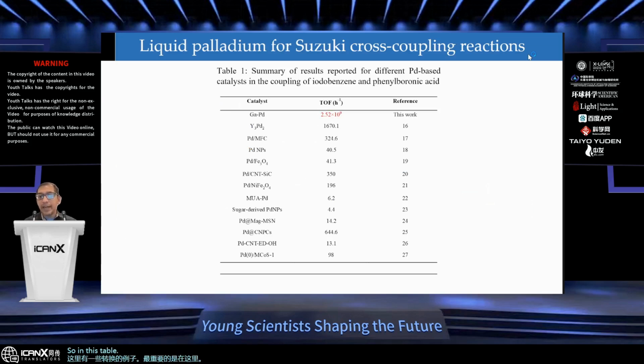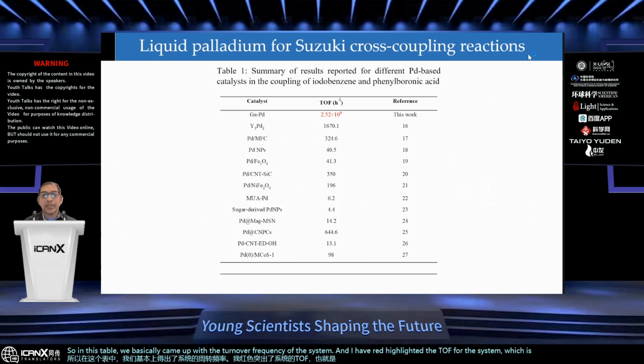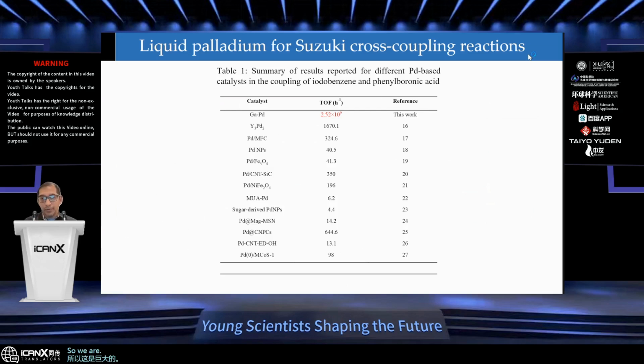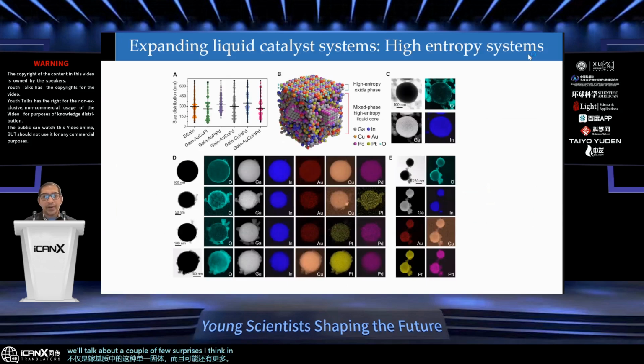So in this table, we basically came up with the turnover frequency of this system. And I have red highlighted the TOF for this system, which is almost 10 to the power 7 times. So 7 orders of magnitude higher than any existing palladium catalyst. So this is huge. So we are looking forward to this, and I believe that not only this single solid in gallium matrix, but maybe many more. We'll talk about a couple of surprises in the next few slides.